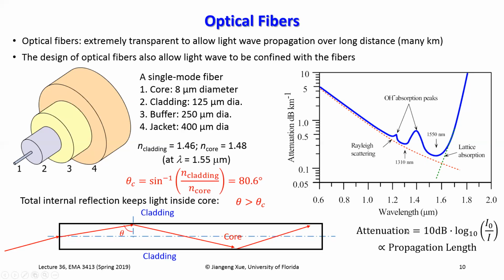This attenuation is defined as 10 dB times the log10 of the intensity reduction. So if the intensity is reduced by 10 times, that corresponds to an attenuation of the light wave by 10 dB. And obviously the attenuation scales with propagation length. So for 50 kilometers, you're going to have about 10 dB, which gets you a 10 times reduction. So 10% of the energy will be able to go through a 50 kilometer long distance. That is pretty long, but obviously we will have to have amplification stages to allow the light wave to propagate to, let's say, Europe, China, and other long distances.